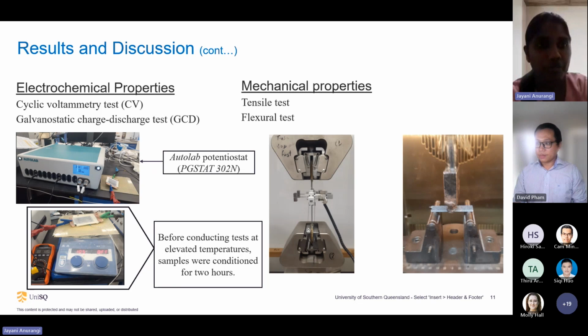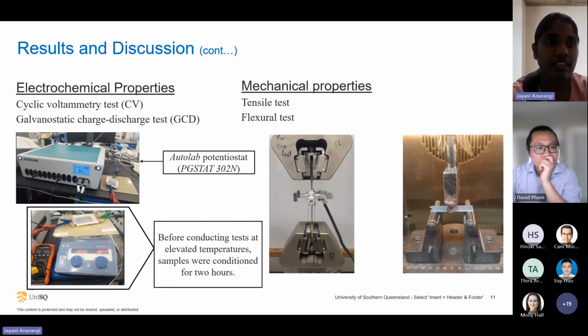When evaluating the performance of the structural supercapacitor, I evaluated electrochemical and mechanical properties. Cyclic voltammetric test and galvanostatic charge discharge test were done to evaluate the electrochemical properties. I used the Autolab potentiostat, which is located in Springfield campus, to measure the electrochemical properties. Mechanical properties were measured based on the tensile and flexural tests.